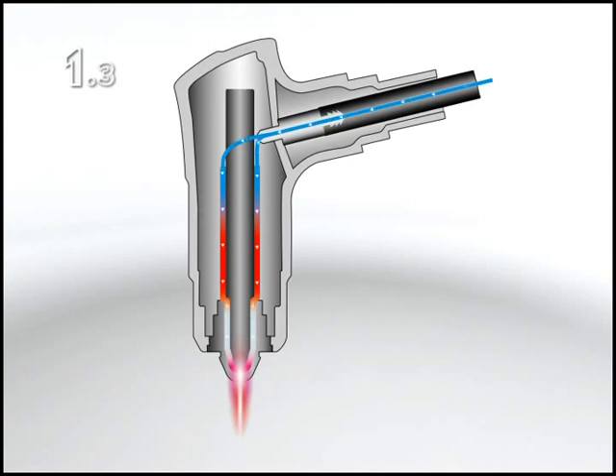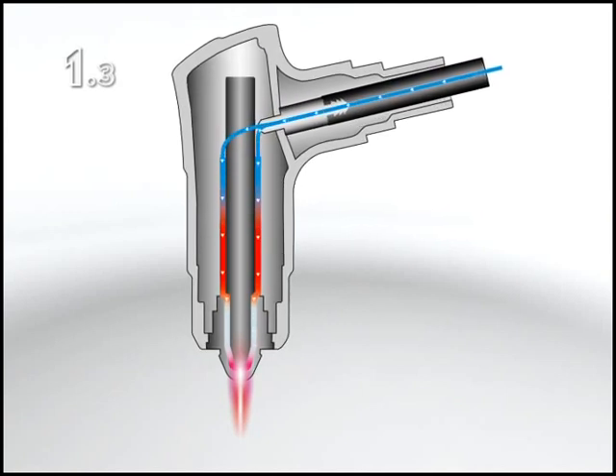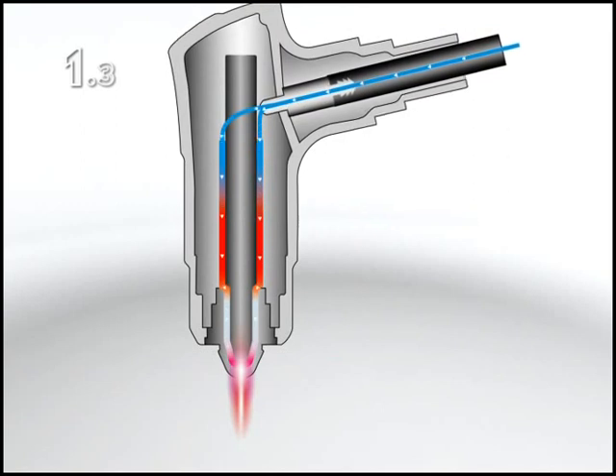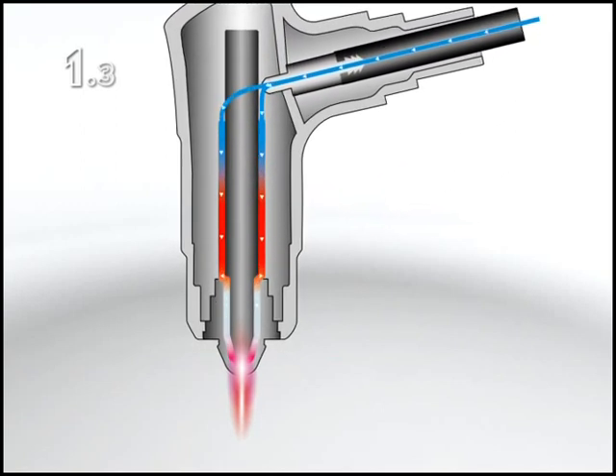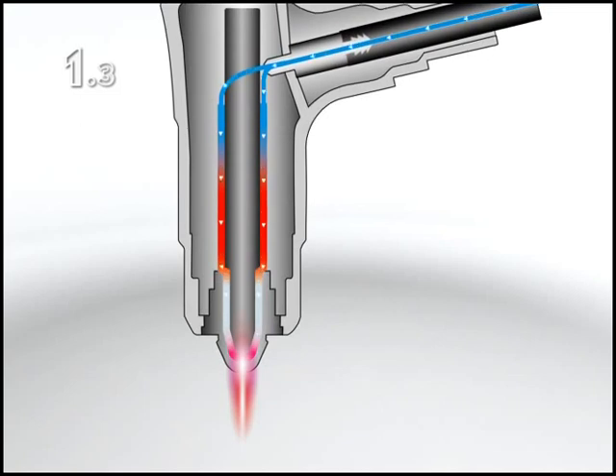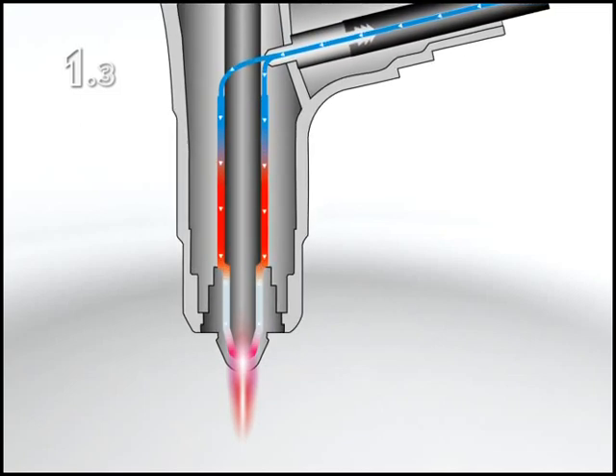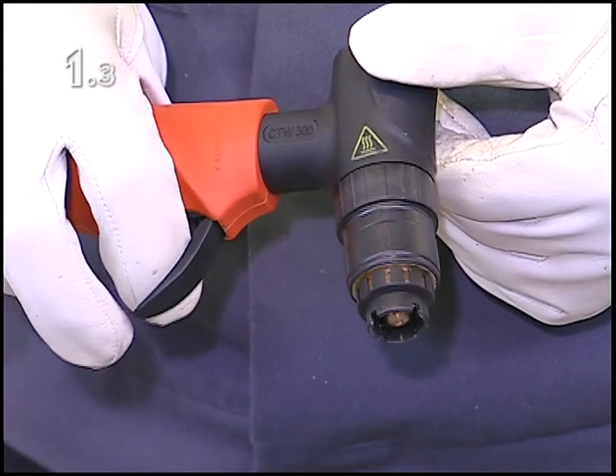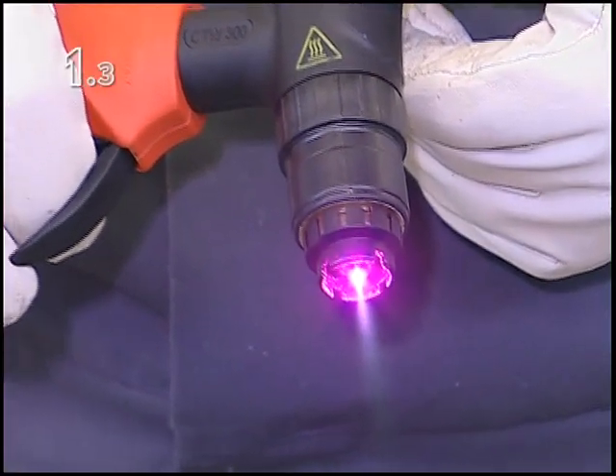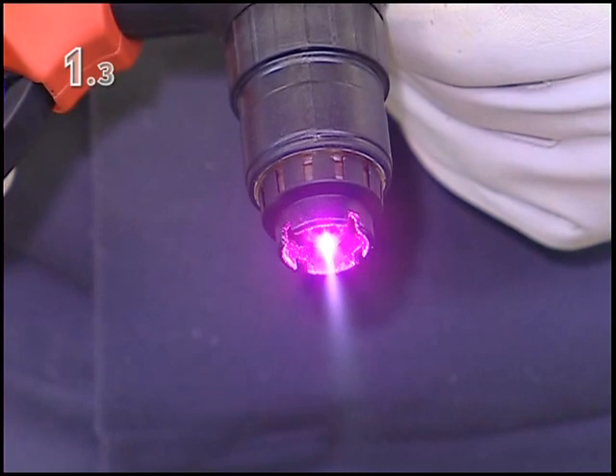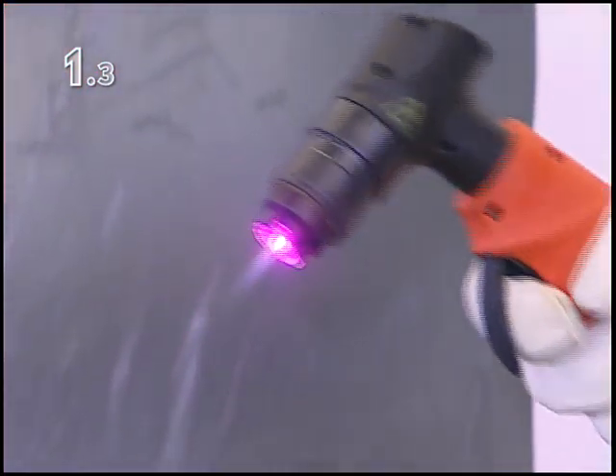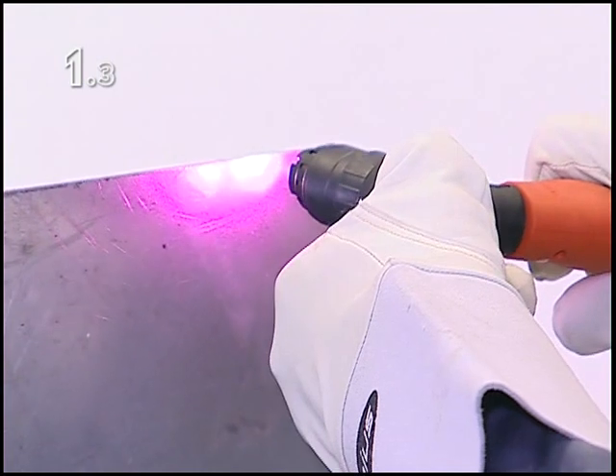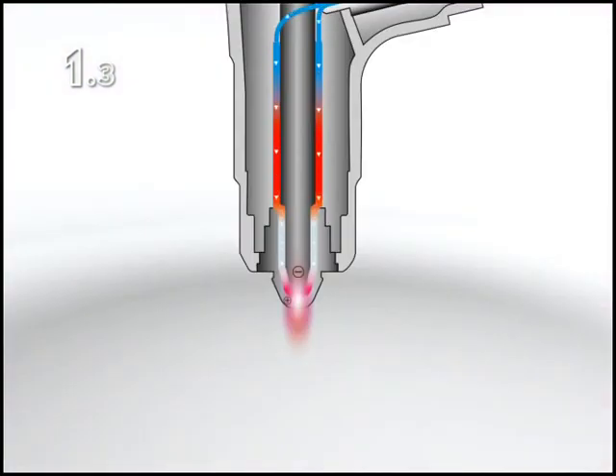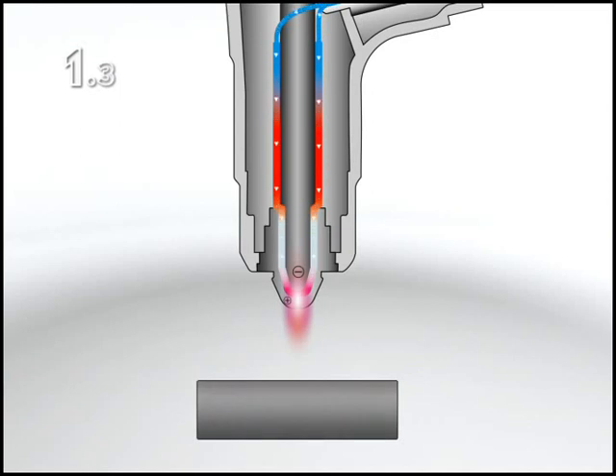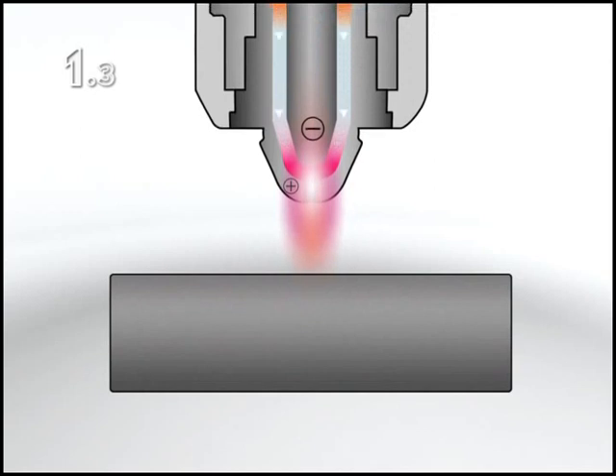Transcut reduces pollutant emissions by up to 90% compared with plasma cutting using compressed air. This makes it possible to work without an extraction system if there is a sufficient supply of fresh air. Pressing the torch safety switch initially generates a pilot arc between the nozzle and the cathode. As the cutting torch approaches the workpiece surface, the power source detects a flow of current in the earth cable and automatically switches from the pilot arc to the main arc.